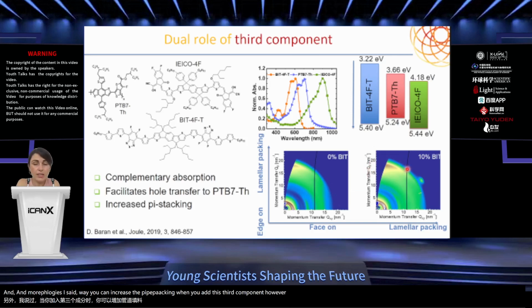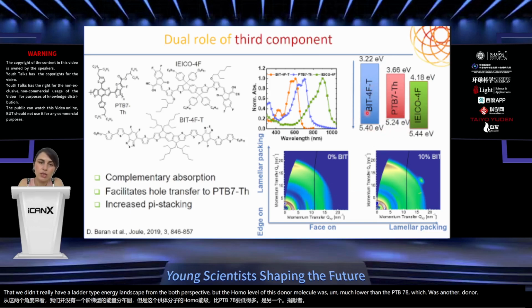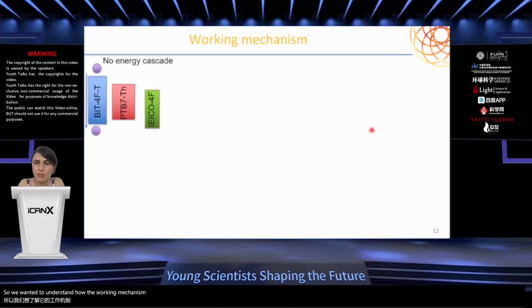However, what was very interesting was that we didn't really have a ladder type energy landscape from both perspectives, but the HOMO level of this donor molecule was much lower than the PTB7-Th, which was another donor. So we wanted to understand how the working mechanism, in terms of energetics, was working here.